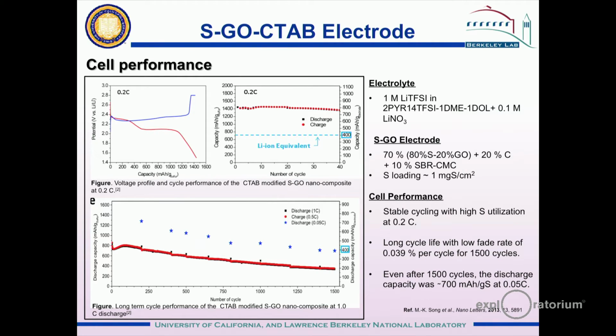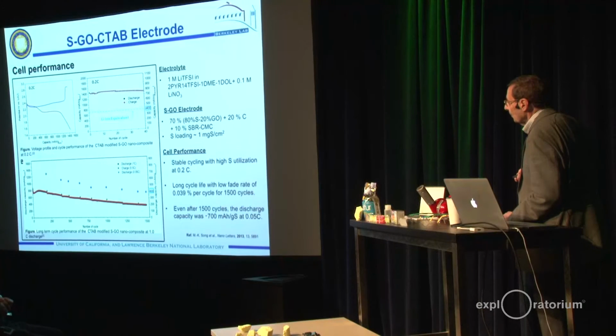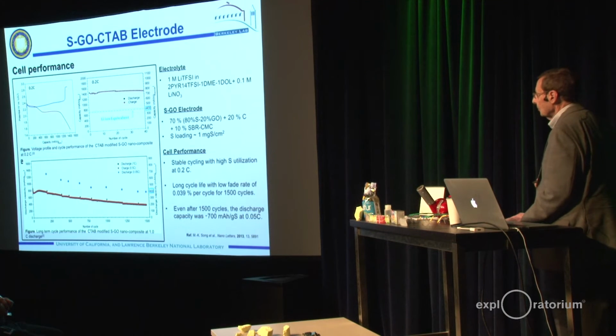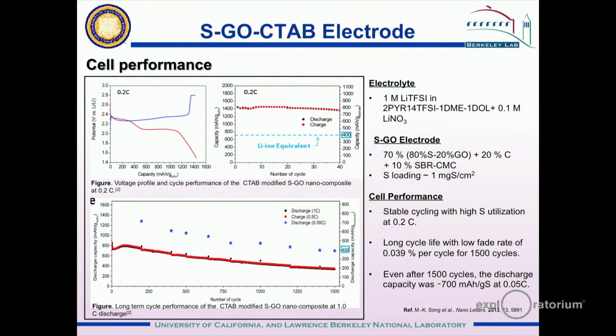Here we show the capacity of the cell as we repeatedly charge and discharge it, and you can see the capacity is very stable over 40 cycles, and we're getting about twice the capacity of an equivalent lithium-ion cell. In this lower plot, we show the very long-term testing out to 1,500 cycles, showing quite good capacity stability. You can see that we are gradually losing capacity in the cell due to minor and slow structural changes in the electrode. But even after 1,500 cycles, we're still getting 700 milliamp hours per gram of sulfur, which is far better than a brand new lithium-ion cell.